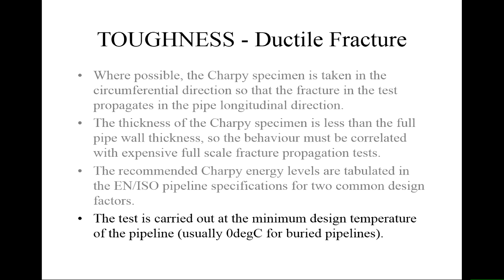So normally we specify a minimum design temperature of 0 degrees C, for instance, for buried gas pipelines in the UK. If you're in the Trans-Canada pipeline where the outside temperature is -20, you'll be using a different minimum design temperature because that's not what the normal consideration is. And if you're putting a pipe in the Middle East in the desert and you're not burying it, again you probably use a lower design temperature because the nighttime temperatures can be very, very low under certain conditions. So you have to know what your local design conditions are to set the minimum temperature, because you need to know what the brittle behaviour is going to be like in these cases.